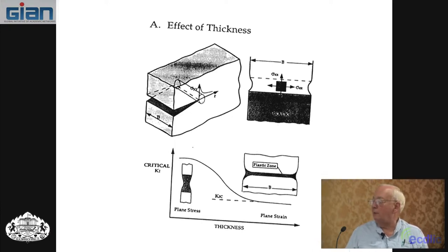Now, the whole K1C concept of having a size criterion is to try to force the specimen to get on this lower plane. If you get on that lower plane, then they theorize that you have a constant value of K for failure that is not dependent on thickness anymore. So here it depends on the thickness. Here it doesn't depend on the thickness anymore. If you get down here, then you get a conservative toughness, and it is a real K1C. What happens if you have a thin structure and you don't want this conservative K1C? You have to do the test at the thickness of the specimen that you have. So you would have to test that exact specimen.